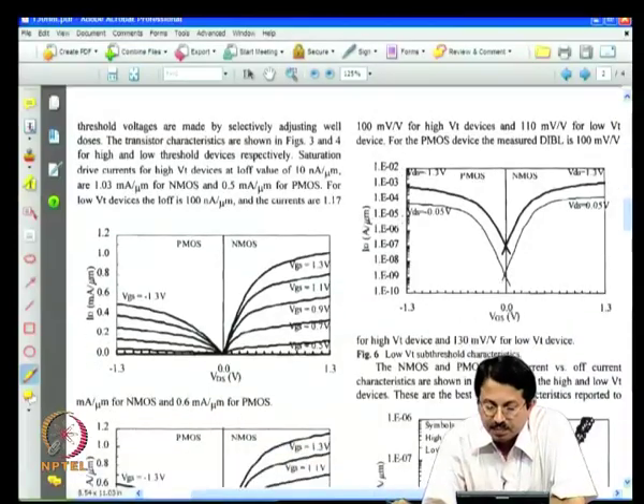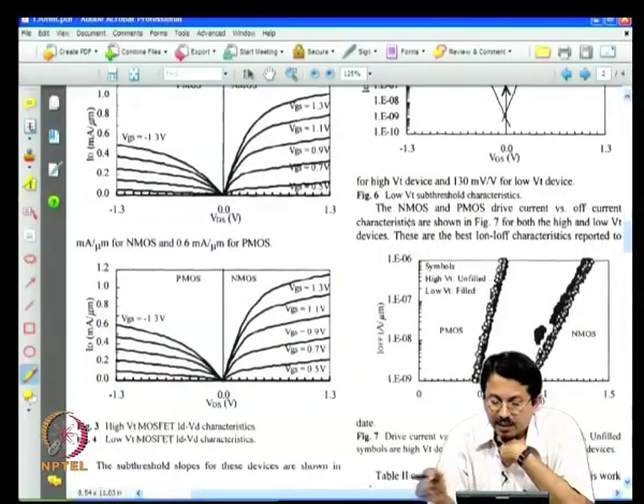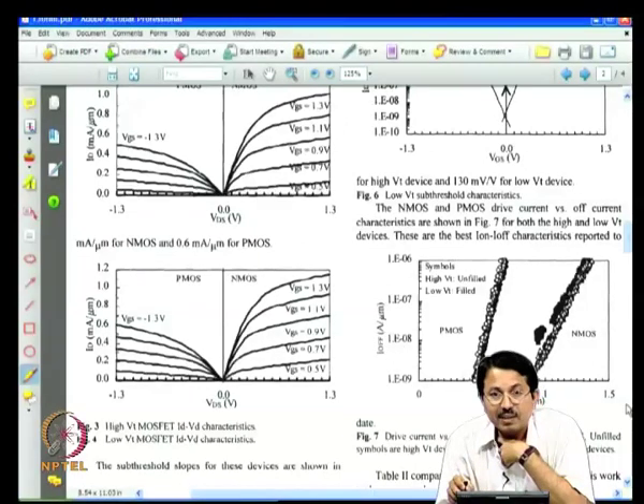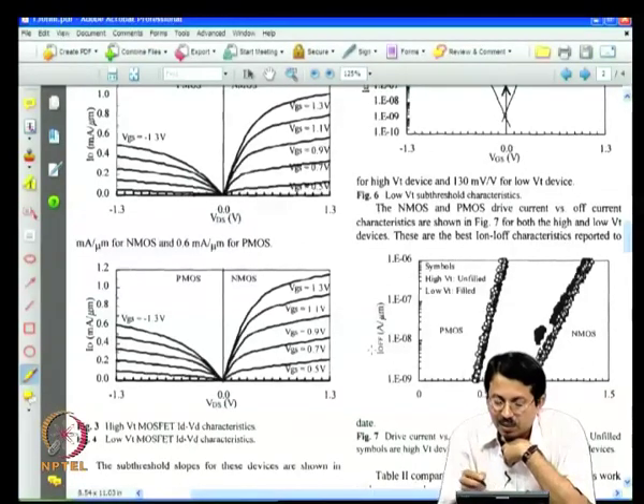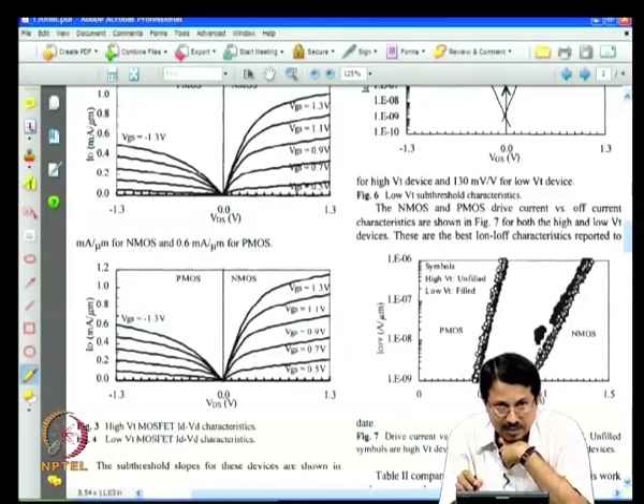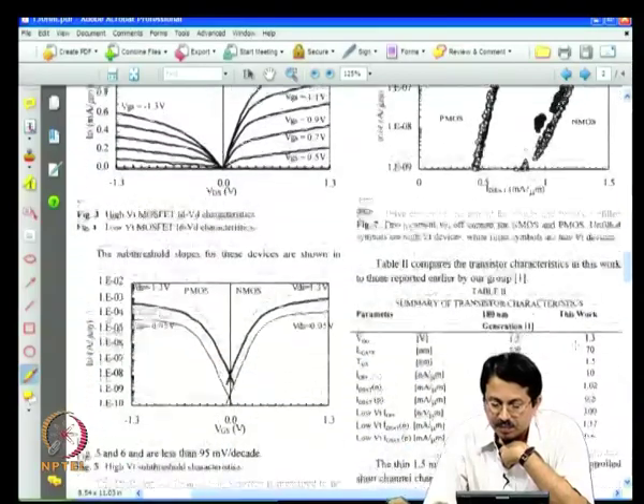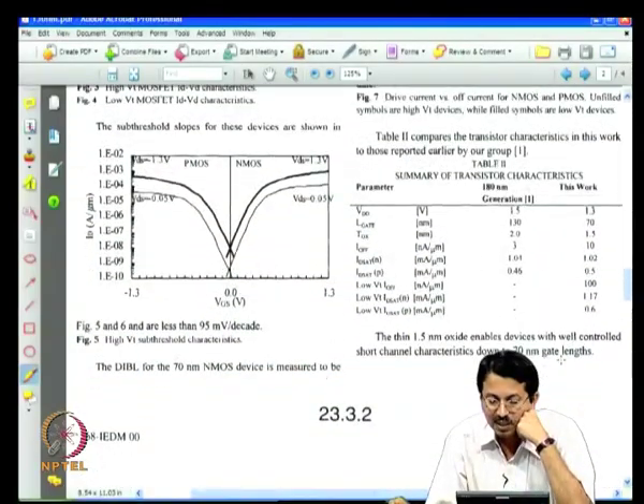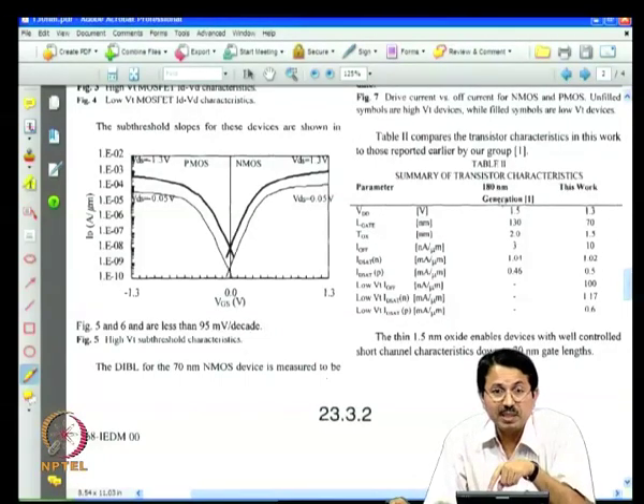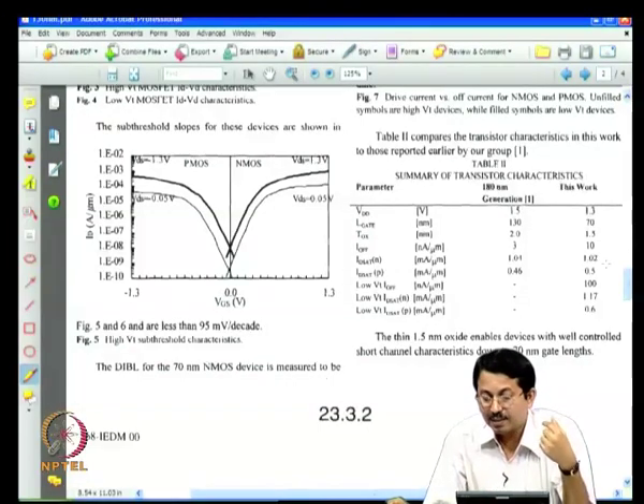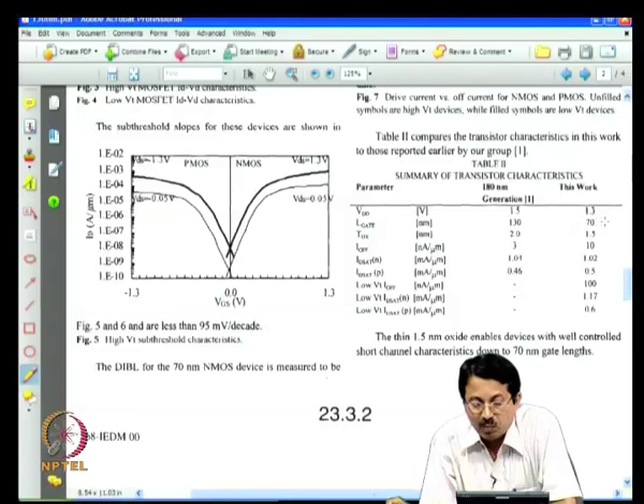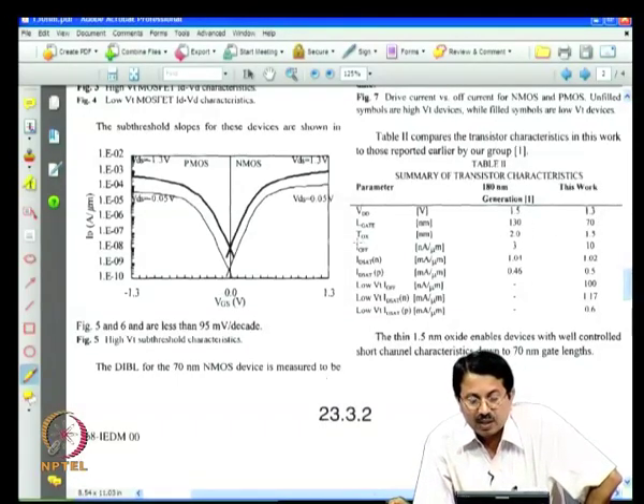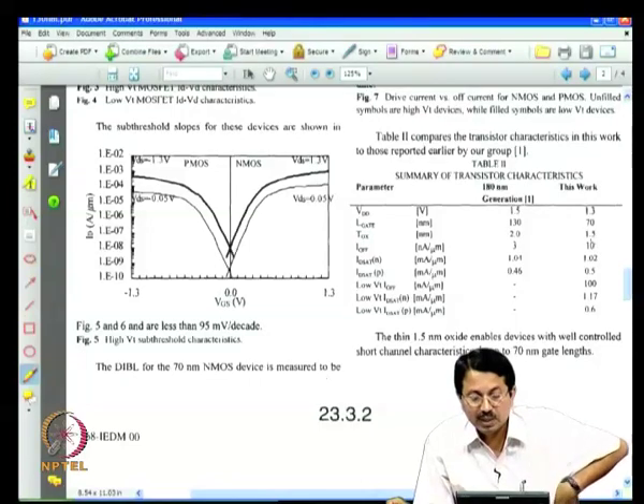And this is again the typical off current versus on current. They are saying that, again two flavors, unfilled and filled, high VT and low VT. There are two flavors of PMOS and two flavors of N channel transistors. These are some important metrics such as VDD, gate length, oxide thickness. They are comparing the 180 nanometer generation, which is a previous paper that we discussed, and this generation. Supply voltage from 1.5 to 1.3, gate length from 130 to 70, oxide thickness from 2 nanometer to 1.5 nanometer, and so on and so forth.